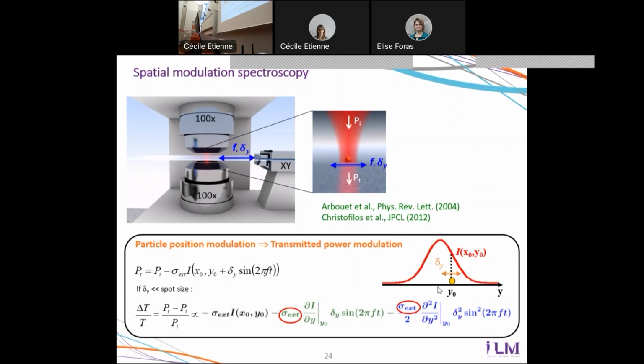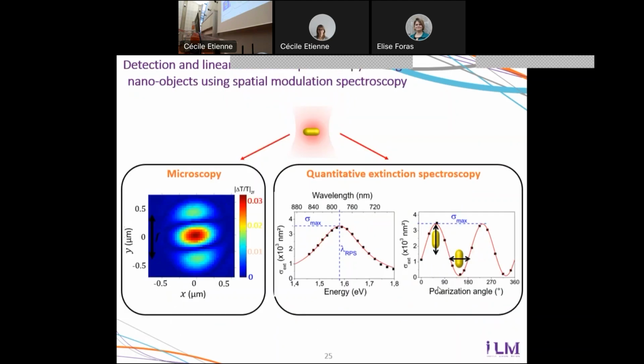So it means that with this tool, we can perform two things. We can perform microscopy, that is, we can make images of the surfaces of our samples. In these images, due to the modulation process, each nanoparticle has a quite specific image. It looks like this: a series of three peaks, an intense one in the middle, and two side peaks at the top and bottom parts. So that's the image of one nanoparticle. And so it means we can detect nanoparticles even if they were purely randomly deposited on the surface.